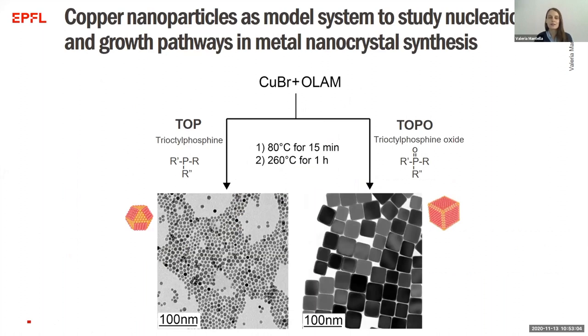What was shown was that we can obtain copper spheres or cubes according to the type of ligand employed. And specifically, when we use trioctylphosphine, copper spheres are obtained. Instead, when we use trioctylphosphine oxide, copper cubes were achieved. And here the most trivial explanation would be that the shape control is dictated by the binding energies of these ligands to the different nanocrystal facets. So this time we wanted to go a bit farther and see if this was the case.